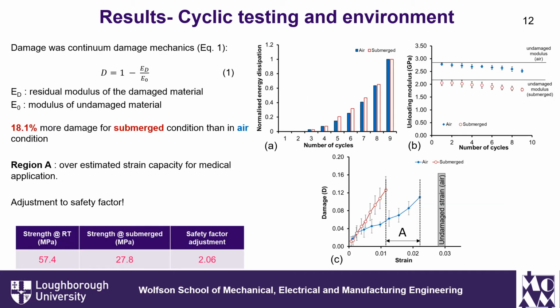After that, we decided to analyze the stress strain curve more in detail. So we plot the energy dissipation as well as unloading modulus and damage evolution for both air and submerged testing. We identified that during the first 4 cycles, the energy dissipation values were comparable. However, after the 5th cycle, submerged testing resulted in more energy dissipation compared to air. For damage, we identified that the values were comparable initially again, and then submerged testing resulted in sharper increase in the damage value, and at the end it was 18% more damage for submerged testing compared to air.